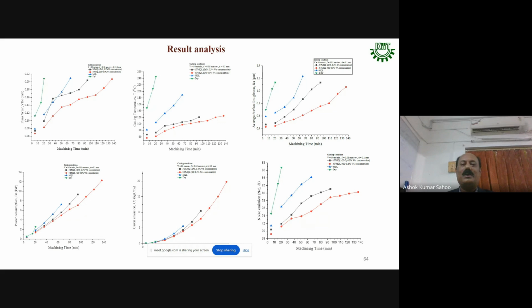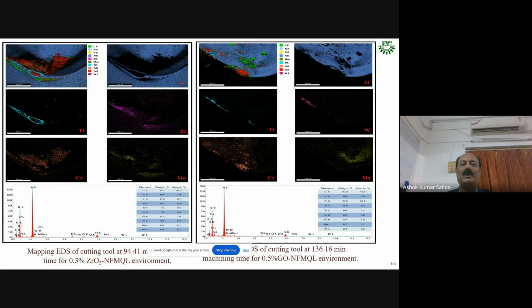And this is the experimental observation of the 4 cutting fluid environments in hard machining, where flank wear progression with machining time has been observed. At 0.5% graphene oxide nanoparticle, the rate of growth of flank wear in hard machining is comparatively lower as compared to the dry environment, the MQL environment, and the ZrO2 nanofluid environment. Similarly, cutting temperature, surface roughness, noise emission, carbon emission, and power consumption during machining are lower for the graphene oxide nanofluid environment at 0.5% by weight.